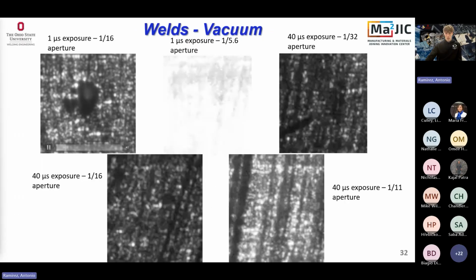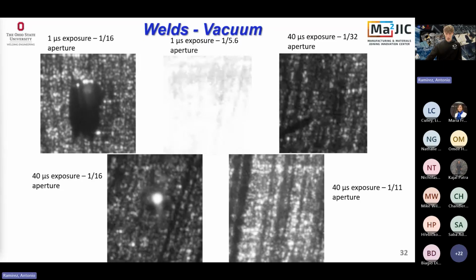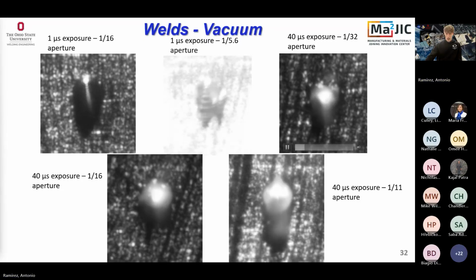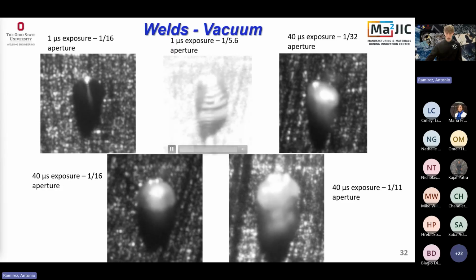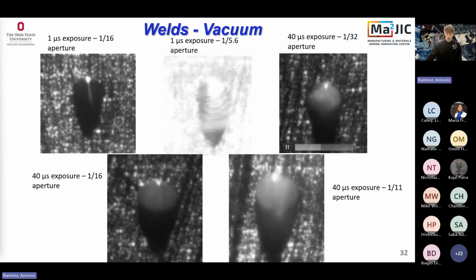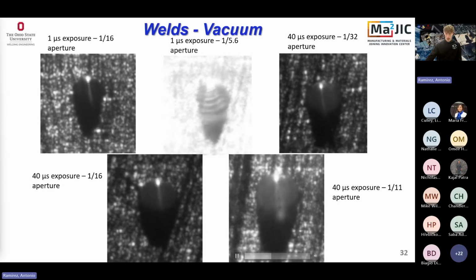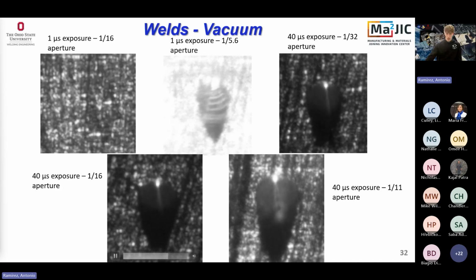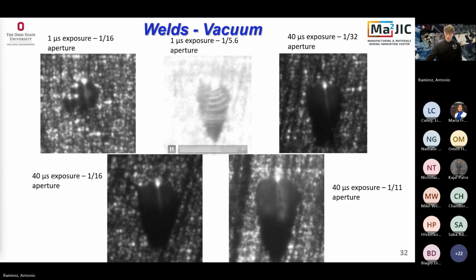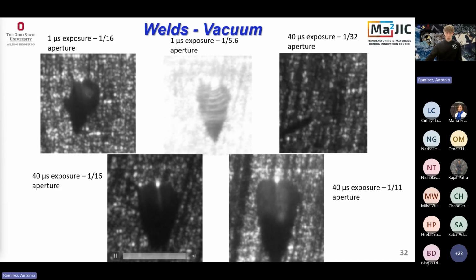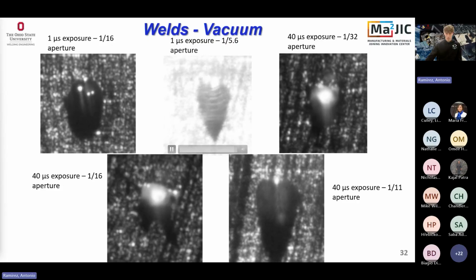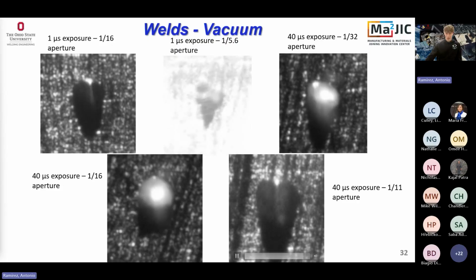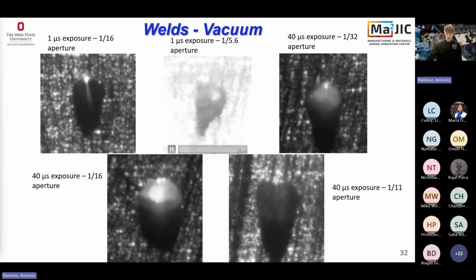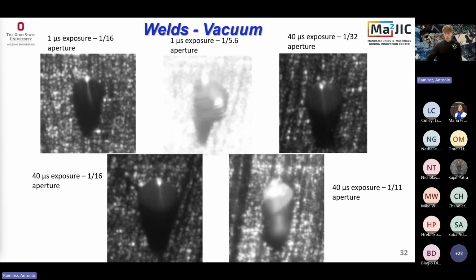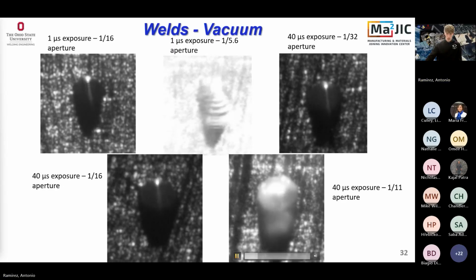Now we go to the vacuum. This is what the results look like under vacuum. As you can see, it's way, way grainier than what we had hoped for. And we messed around with the exposure time and aperture to try and get the best results. But because of how the viewport works and some other things, the quality didn't turn out as good as we'd hoped, but it is still enough data to calibrate our models.